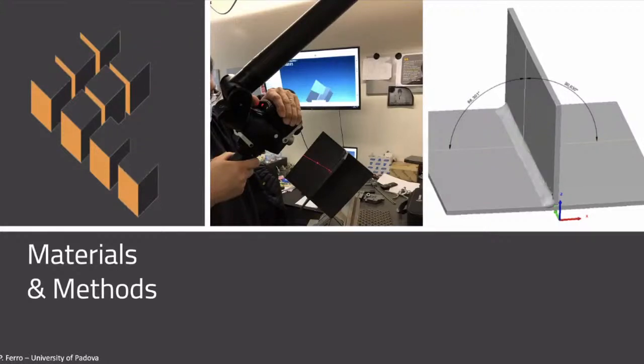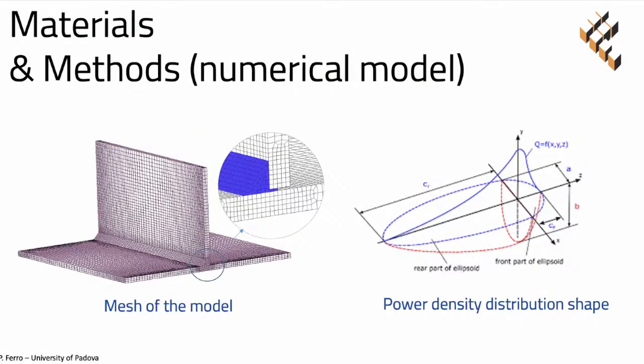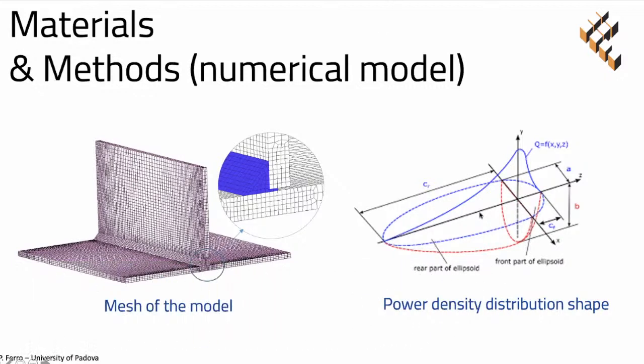This is the model, the numerical model. It was performed by using the Sysweld numerical code. We divide the elements into 2 different groups: the base material, the parent material, colored in white, and in blue you can see the elements that we use to simulate the bead. And these elements are activated when the source comes over the elements. We use as a source the very famous Goldak heat source that has a double ellipsoid power density distribution function.